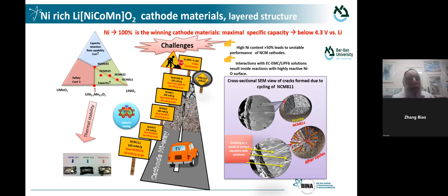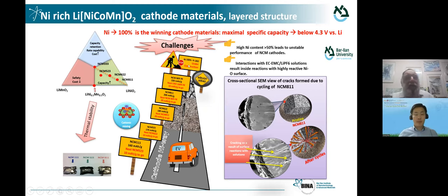The first example is what you call nickel-rich NCM. Here we are talking about 5 elements: lithium, nickel, cobalt, manganese, oxygen. Lithium stoichiometry is 1, the transition metal stoichiometry is 1, the oxygen stoichiometry number is 2, and as we increase the amount of nickel, we increase the possible specific capacity of the material. This is illustrated here in this cartoon. We go up the row, and you have the numbers in the small placards. If we go, for instance, up to 100% nickel, the so-called LNO, then we can start with 250 milliampere hour per gram.